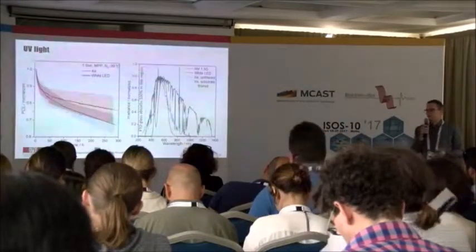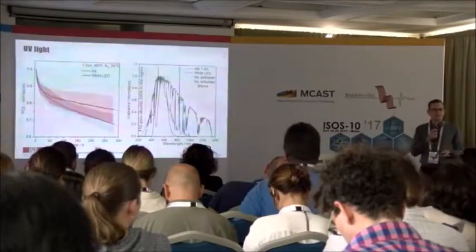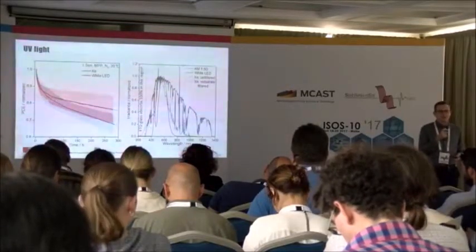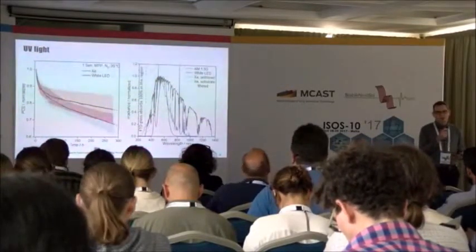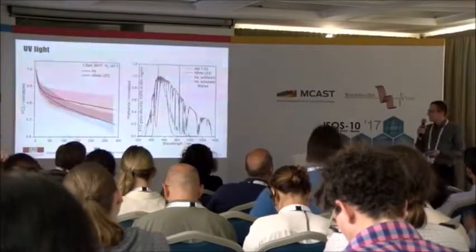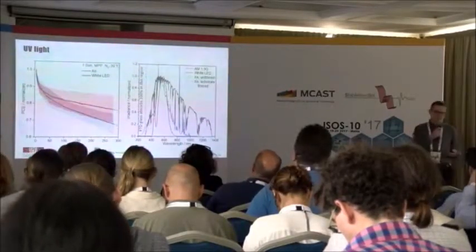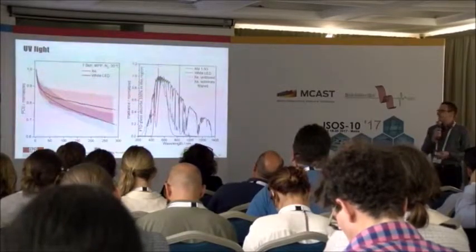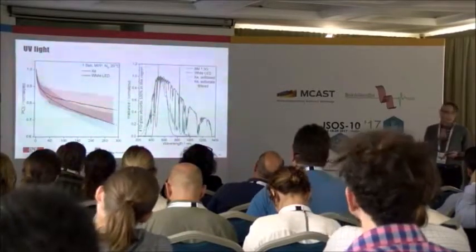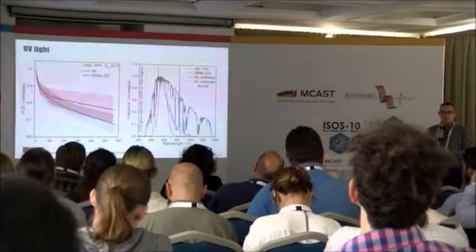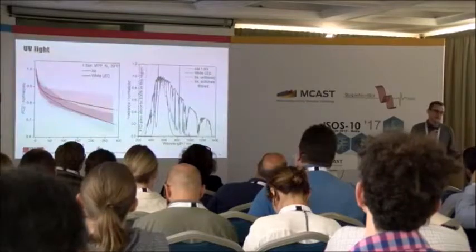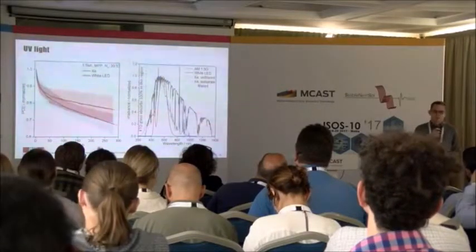And in a way, we investigated the worst possible scenario because we're using TiO2, which is speculated to degrade the cells a lot. So the message here is that, yes, UV is worse for perovskite than LEDs, but it's not catastrophic. So we did the rest of the studies under LED to deconvolute the UV degradation from the other intrinsic